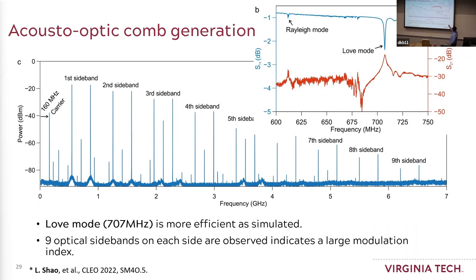The figure B here shows that we have a relatively good Q factor of the acoustic mode at the frequency we want, as seen from the S11. The red line indicates the transduction from the acoustic domain to the optical domain, and we can see it is enhanced by almost 10 dB at the resonance frequency. And this is one thing.